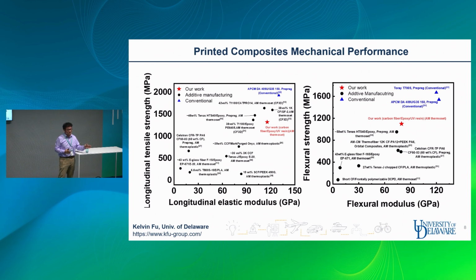The performance of the composites is actually determined by two things: resin and carbon fiber. But we are using a kind of low quality carbon fiber. If you look at other results, they are using Toray T1100. That is a super high performance carbon fiber. So based on our very rough calculation, if we can use similar carbon fiber, our performance could be much higher than any of the existing 3D printed composites.